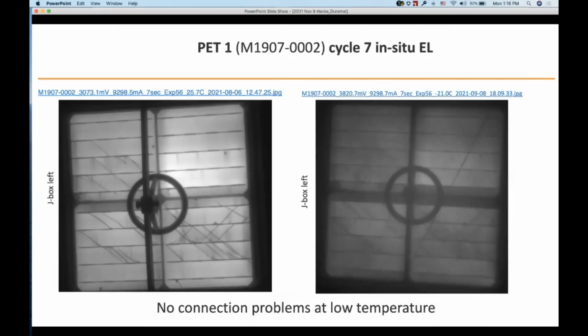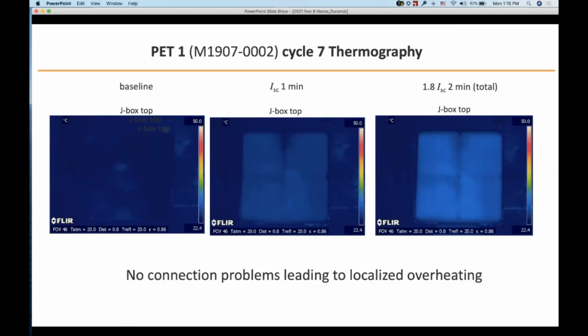And that's also true at various temperatures. So here we're looking in situ electroluminescence here at room temperature and here at minus 20 degrees. And it's a fairly similar story. We don't see much of, you know, any important areas dropping out. This line here is actually a string, not a crack. So there's really no connection problems at low temperature either.